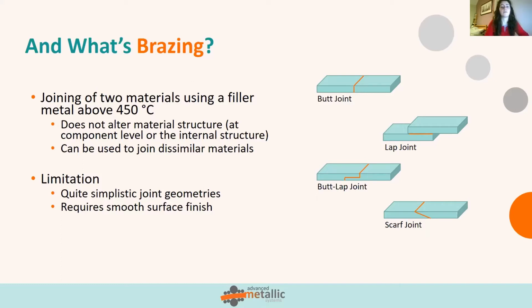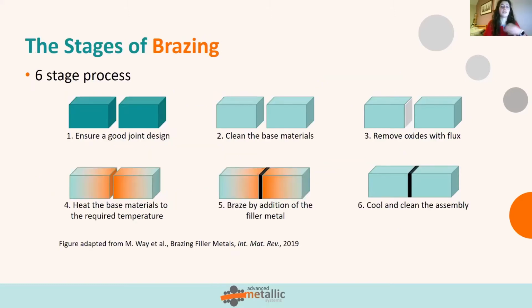In terms of the stages of brazing, it's a six-stage process. First, you need to ensure that you've got a good joint design. You need to make sure that the base materials are cleaned of anything like oil or grease that might have been put on them during the manufacturing of the base materials. Then the oxides are removed with a flux.